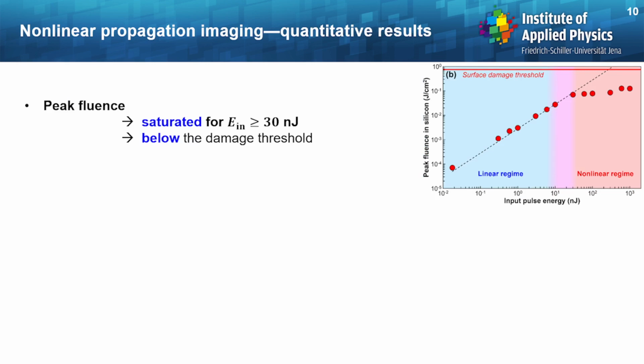Okay, this was the qualitative picture, and then quantitatively one can easily measure with these experiments the peak fluence in the bulk of silicon as a function of the input pulse energy, and those are the red points that you can see here. One can see that at some point, after 30 nanojoule, there is a saturation of the energy deposition in the bulk of silicon, and it appears to be below the surface damage threshold of silicon. So it's not possible to modify the material quite easily in that case.